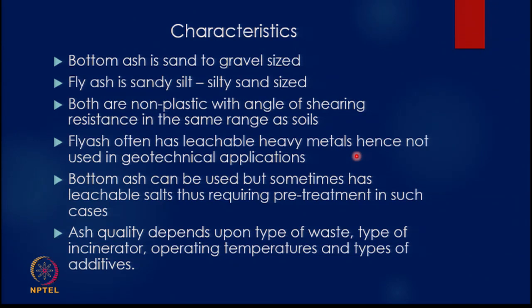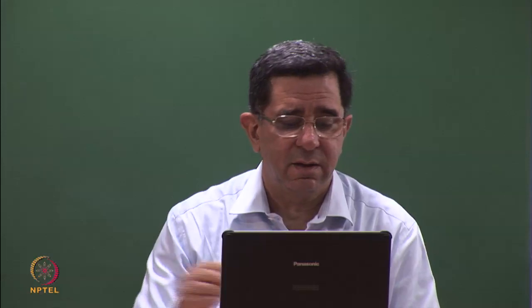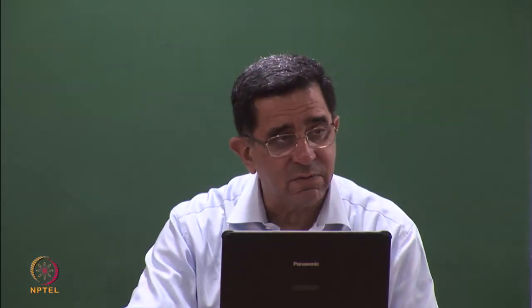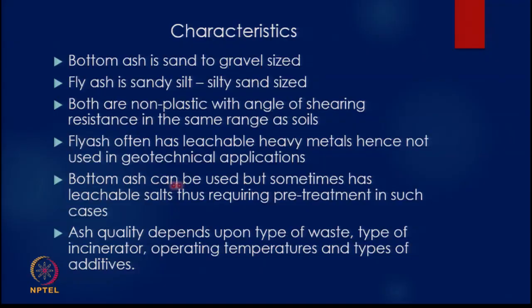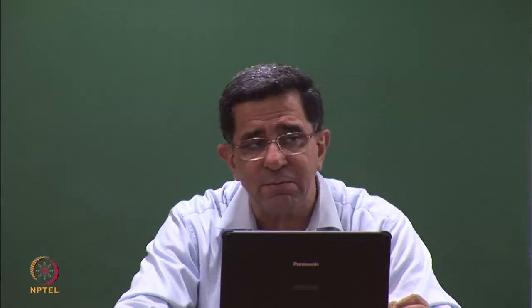In coal ash, it is still not 100% clear that all fly ashes have leachable heavy metals. Though America is now saying that from the ash pond, some unusual heavy metals are leaching out. But here, in MSW ash, in the fly ash, which is a low percentage, the metals get volatilized in the furnace, they go with the flue gases, and when the flue gases are caught with the ash, they deposit themselves on the fly ash. Bottom ash can be used in geotechnical applications, but sometimes has leachable salts, and therefore you may need some treatment or dosing of the bottom ash for earthworks. But in the bulk of the cases, bottom ash is reusable with some nominal pretreatment.